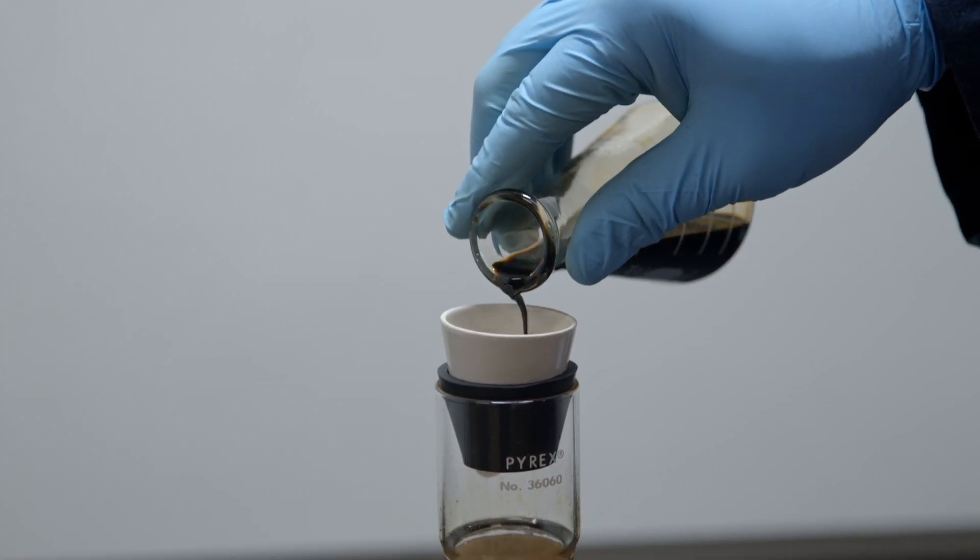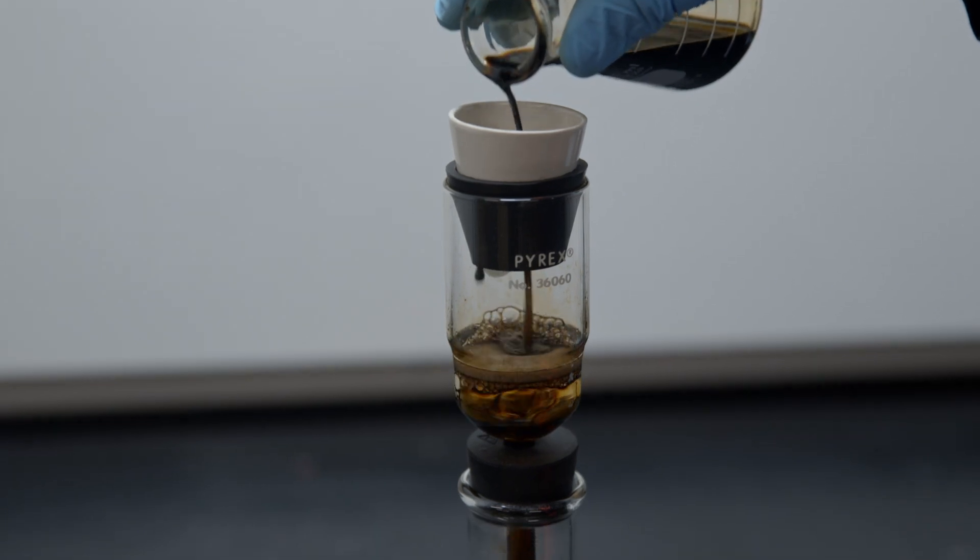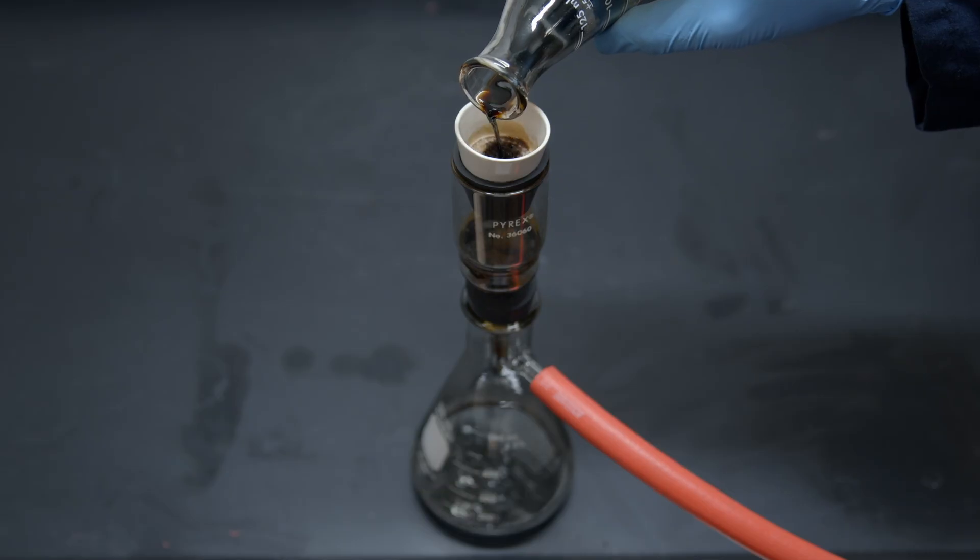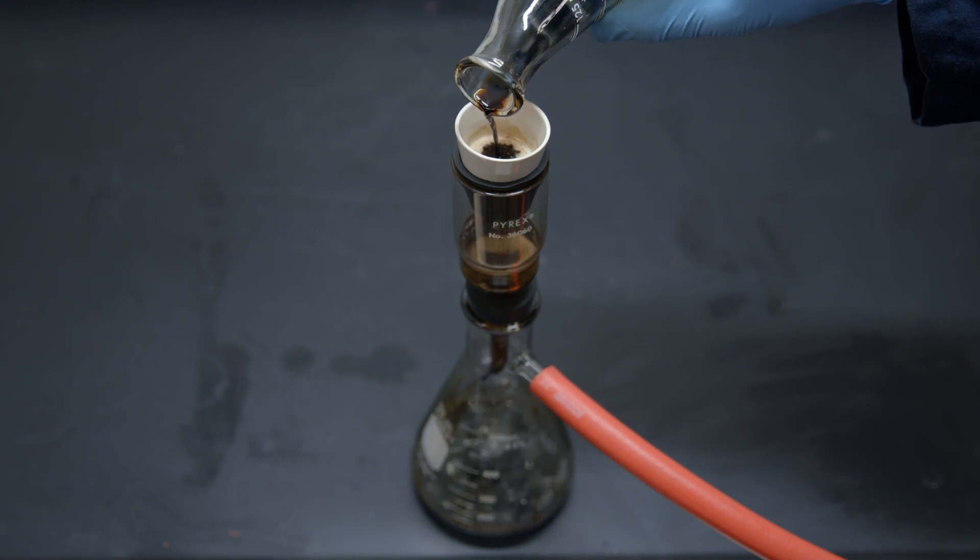Using light suction, decant the sample dissolved in solution through the pad. Retain as much insoluble matter as possible in the container until the solution has drained through the filter pad.